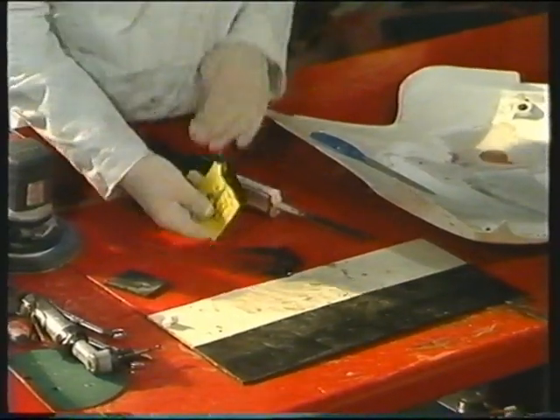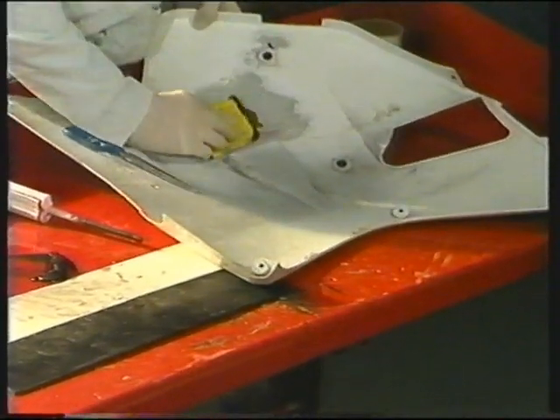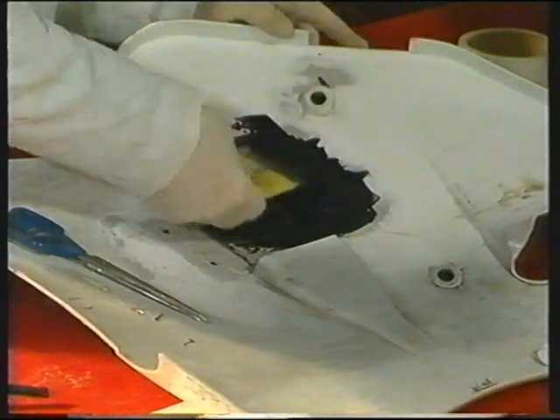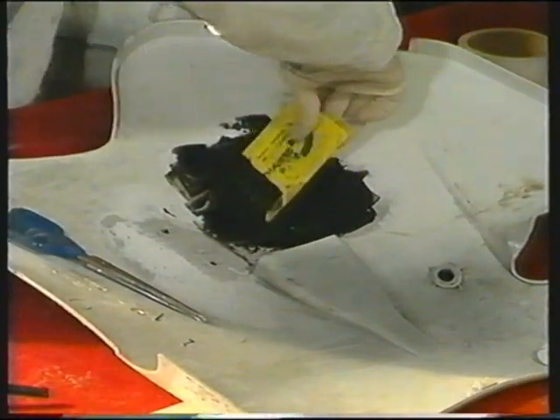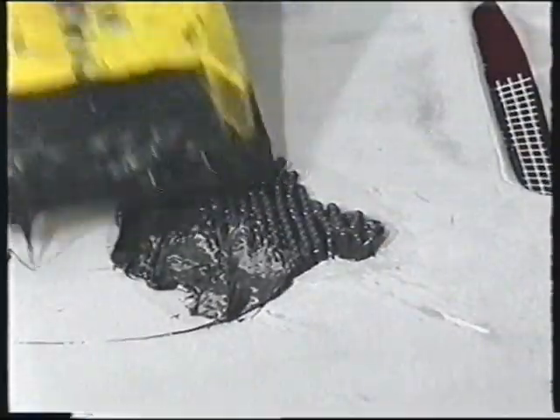Terramix 6700 is a two-component chemical curing adhesive. It's applied over the back of the gauze, thoroughly saturating it and extending over its edges. As the adhesive is pushed into the gauze, it oozes through to the front of the fairing, where it's smoothed out to overlap onto the surrounding plastic.